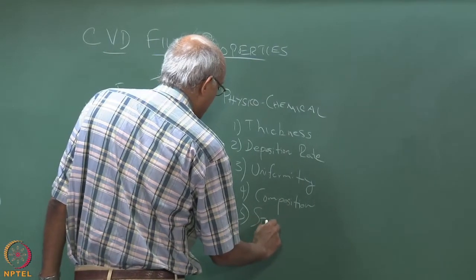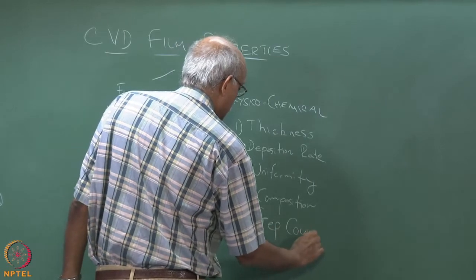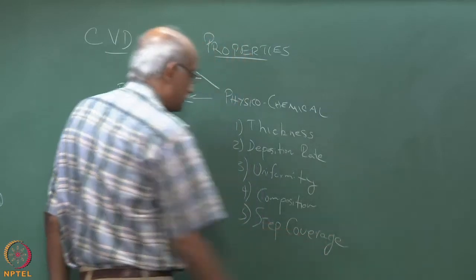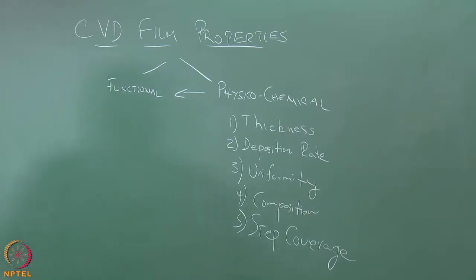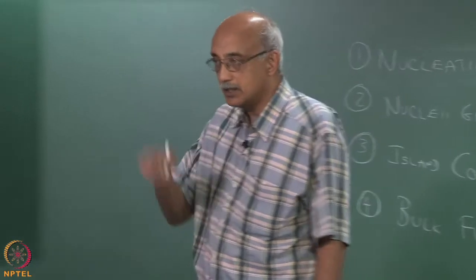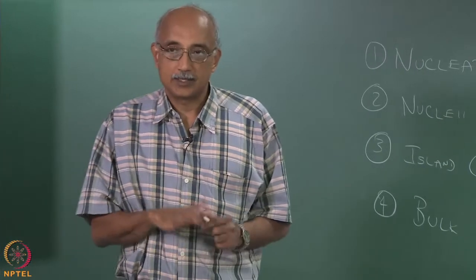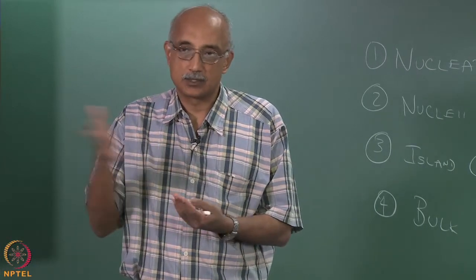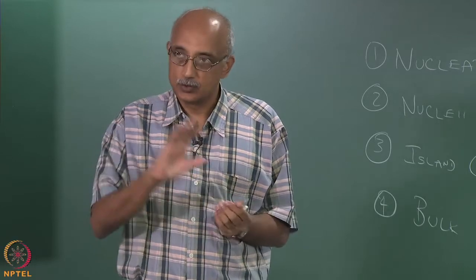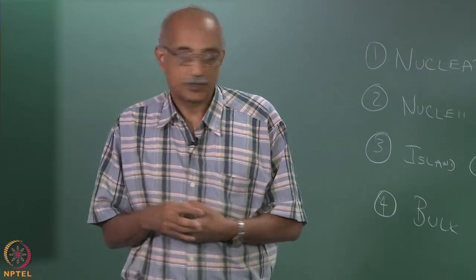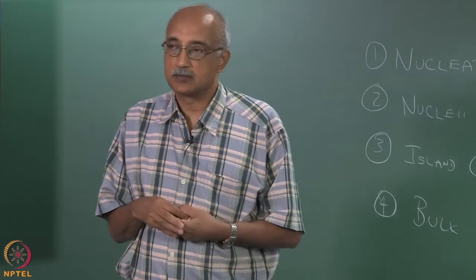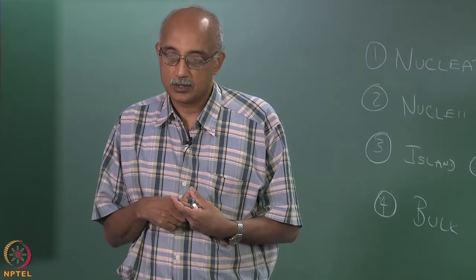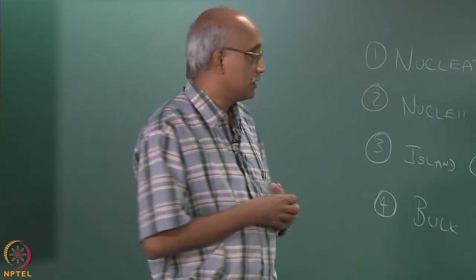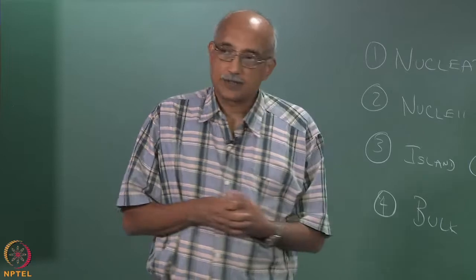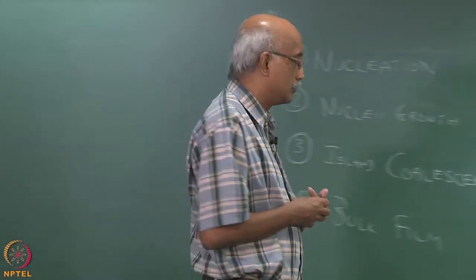So related to the uniformity is what we would call step coverage. If your substrate has certain features on it, particularly steps, how well is the CVD film able to follow this step structure and provide uniform coating thickness everywhere? So this step coverage is another important parameter when we are trying to characterize a CVD process. What are some of the other parameters that could be important?